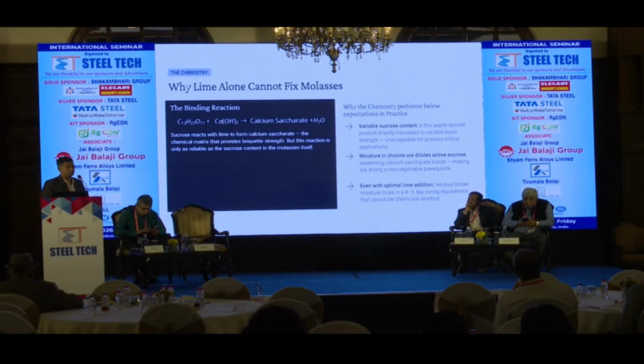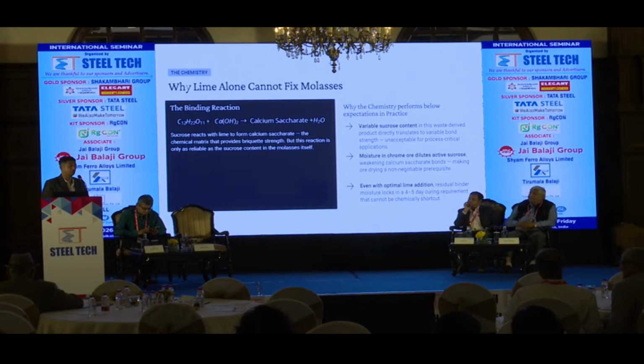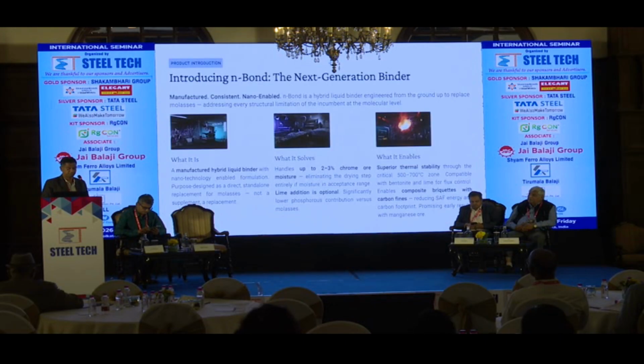So 3 key points. Variable sucrose content. It's not a product, it's a byproduct or waste product. So there's a lot of variability in the sucrose content which affects the strength from batch to batch and from plant to plant. The moisture in the chrome ore dilutes the active sucrose. That dilution again leads to a loss of strength. Even with optimal lime addition, you require minimum 5 days of curing time.